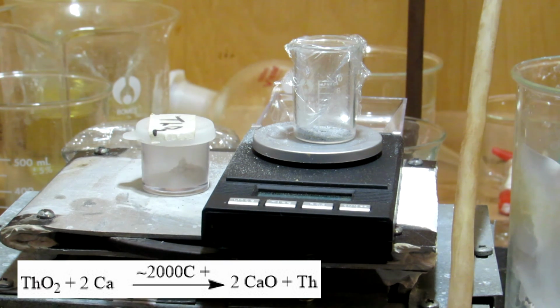To convert the thorium dioxide to thorium metal, we can reduce it with an excess of calcium metal at high temperatures in my homemade arc furnace. The arc furnace was made by rewinding the coils on an old 45-pound iron core transformer that I found behind a dumpster. To prevent reoxidation of the thorium, I added some sodium carbonate on top of the thorium and calcium to protect it from the atmosphere. The sodium carbonate decomposes to sodium oxide at high temperatures and protects the thorium that is formed.